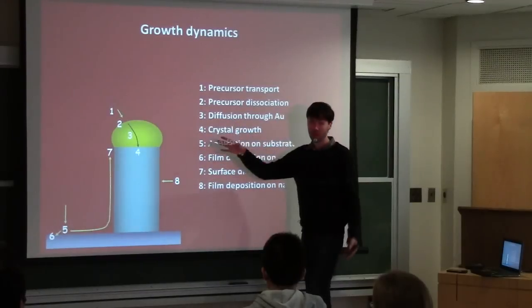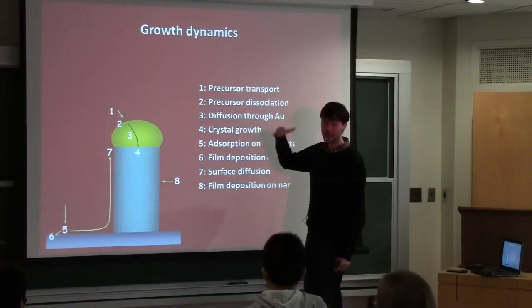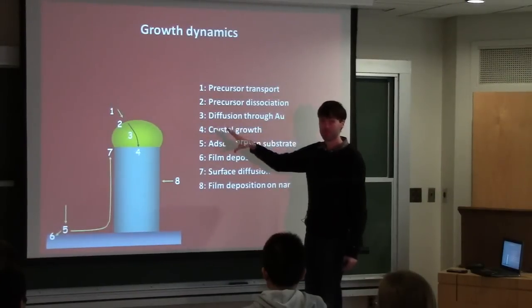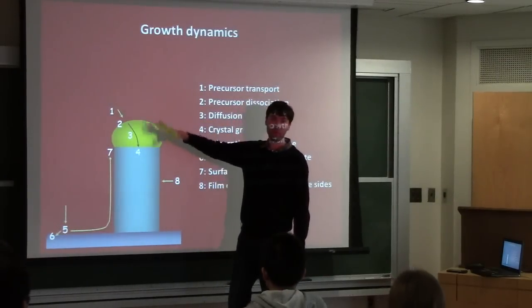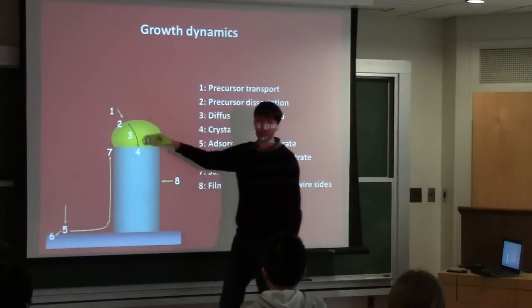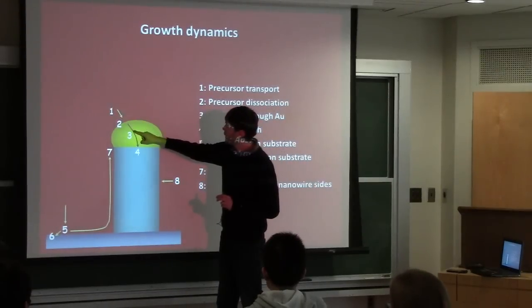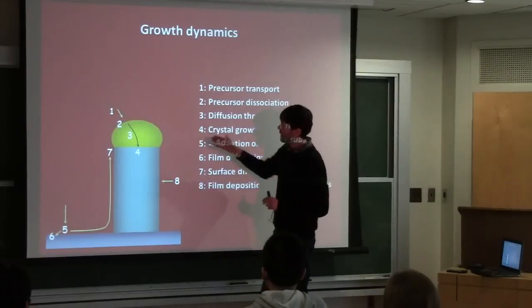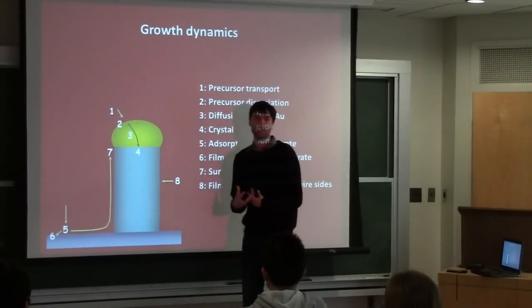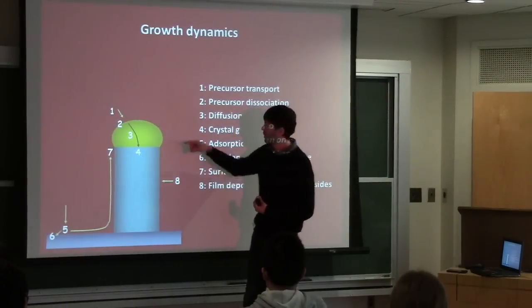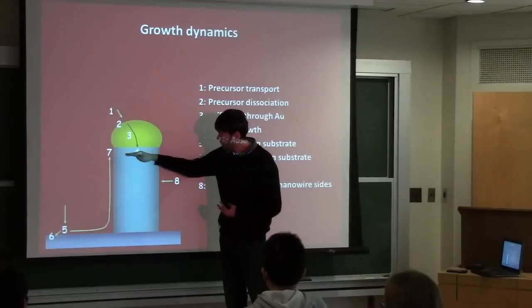So the way it happens is, we are not in high vacuum, we have all these precursors flying around, and at a certain temperature where this process is favored, when the precursors like trimethyl indium and arsine hit the surface of the catalyst, they decompose. So they throw away all the organics, all the hydrogens and carbons, and then they go into the gold. And then it becomes a gold alloy, for example, gold indium alloy. And then that alloy keeps absorbing indium until it reaches a certain supersaturation point, after which indium precipitates underneath the nanowire, combined with arsenic. So indium arsenide precipitates underneath and pushes the gold particle up, and so the gold particle moves up, leaving behind this nanowire.